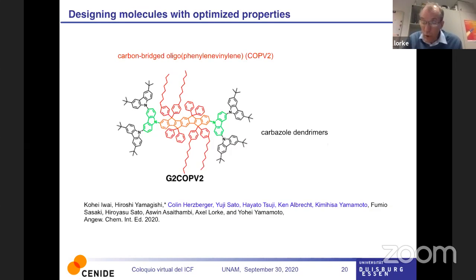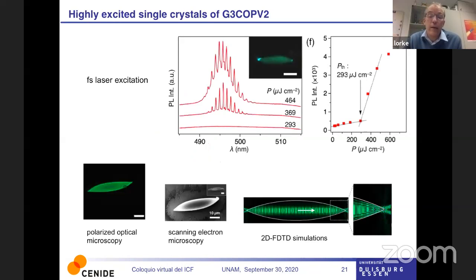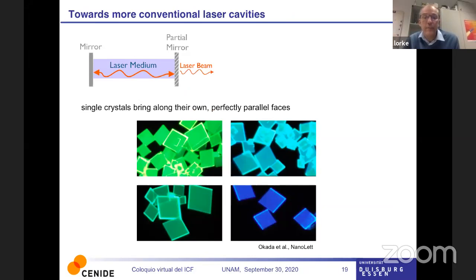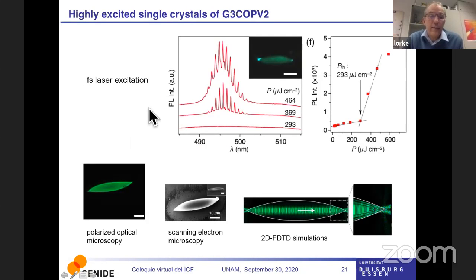And this stuff worked really well, and they were able to crystallize it. I had shown you a similar compound in this slide. This is generation 3 COPV2, and this has a very interesting way to crystallize because the facets here are curved. So in this respect, it looks like it's not really a crystal, but they were able to do X-ray diffraction, and they say on the inside, it's nicely crystalline.